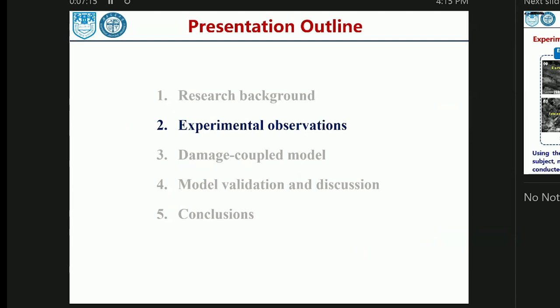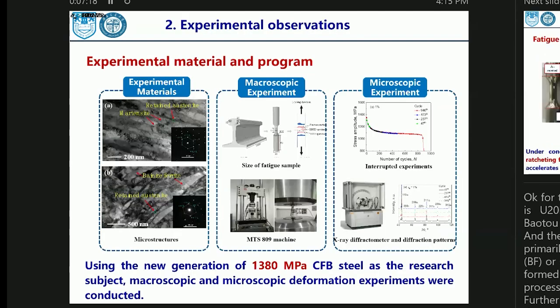Let's see some observations of the experiments. The test material is U20Mn CFB rail steel, and the microstructure of the CFB rail steel primarily consists of lens-like bainitic ferrite and sheaf-like lower bainitic ferrite formed through bainitic transformation. The TEM observations in these figures reveal that both bainitic ferrite and the martensitic lens exhibit a lens-like morphology, and the thin film-like retained austenite is in between the lenses.